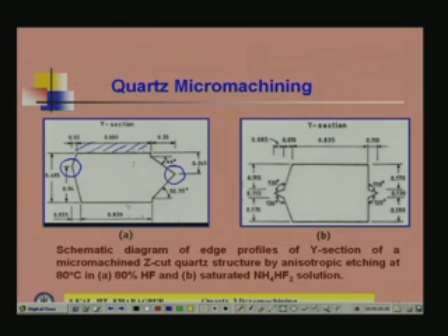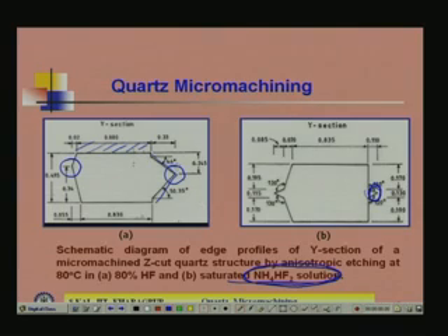Now, if you use another etching solution, which is saturated ammonium fluoride solution, then you see in the right side B curve, the kinks and facets have reduced to a small one. Here it was a large kink, here it is a small kink. And now, at the same time, if you go for low temperature etching, then those things will almost vanish. With low temperature etching, the etch rate may be very slow, so you have to allow longer etching time, but you can get rid of this kind of problem